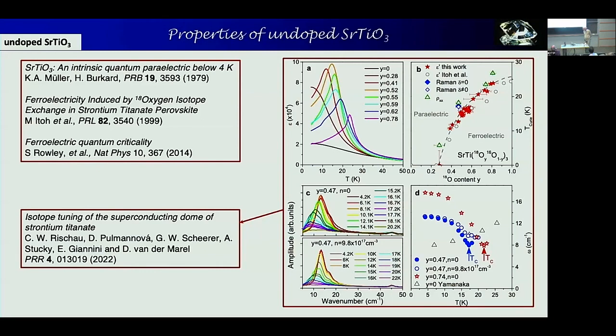And actually in 1979 already it was proposed by the now late Karl Alex Müller that this material was a quantum paraelectric below 4 Kelvin, meaning that it's a system that without quantum fluctuations would decide to go ferroelectric, but for reasons somewhat similar to why helium doesn't become solid at ambient pressure, it actually doesn't become ferroelectric at low temperatures. However, it's relatively simple in this case, because it is close to becoming ferroelectric, to push it in that direction.